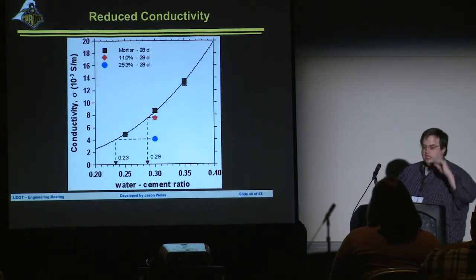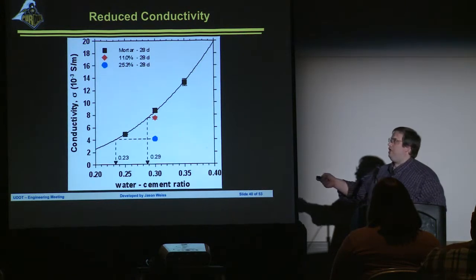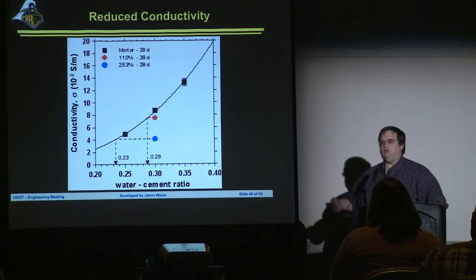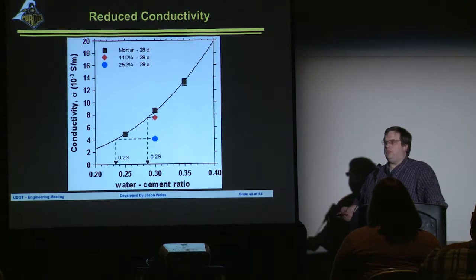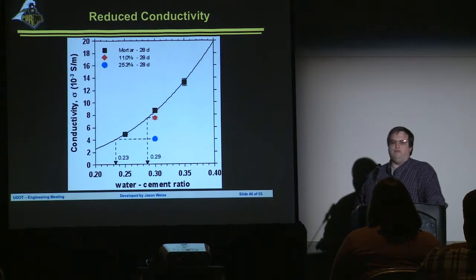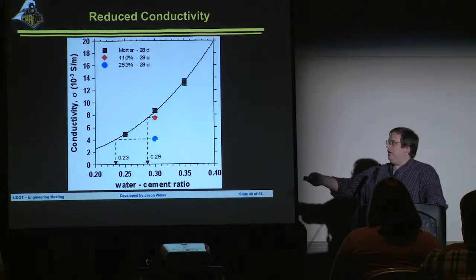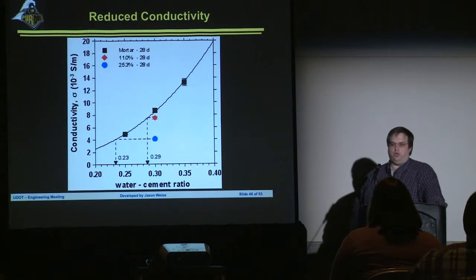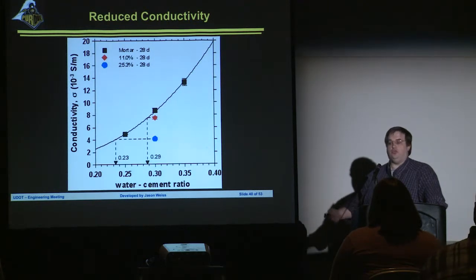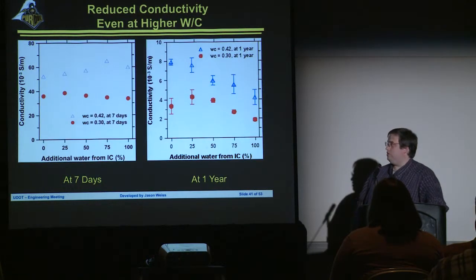Same thing happens with electrical conductivity. Electrical conductivity, you may say, well, we don't use electrical conductivity, we have other measures here. This is essentially the inverse of the rapid chloride permeability test, the 1202 or the RCPT test. Again, a 0.3 behaving like a 0.23 because we've got increased hydration happening in the overall system.